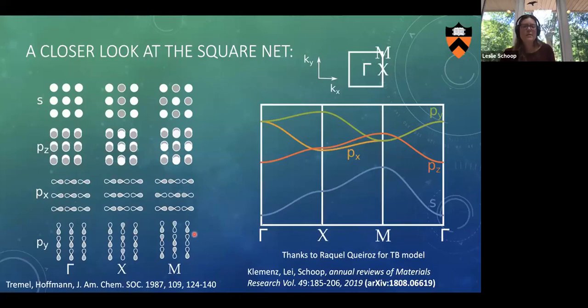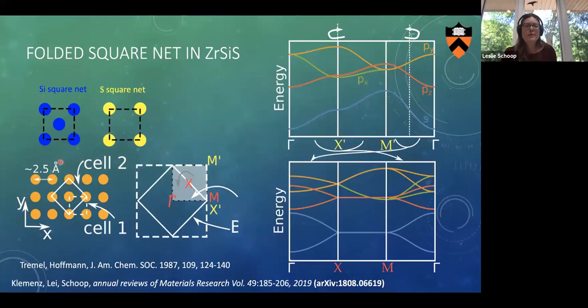Not until you look at the crystal structure, which in the hypervalently bonded square net actually also has 2 atoms per unit cell, because the unit cell is defined by other atoms. And because it has 2 atoms per unit cell, this band structure needs to fold. And then it gets these beautiful crossings here. Okay, so the lesson we learned from this is we need 2 things. We need electron delocalization, and we need 2 chemically equivalent atoms per unit cell. And then we can have linear band crossings that are at the Fermi level.